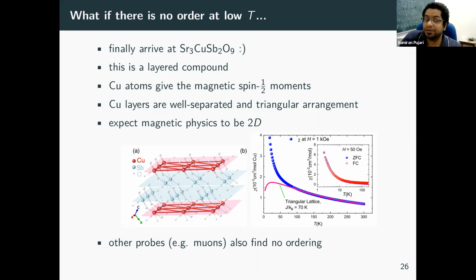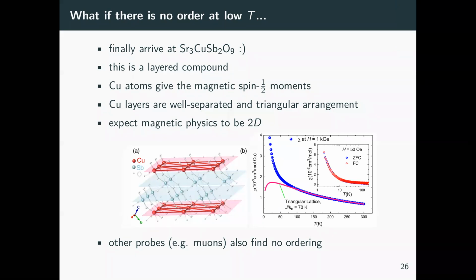That question can be asked even for an unfrustrated square lattice, right? Say I had a pure square lattice. So here it turns out that this goes under the name of Chakravarty, Halperin, Nelson theory. Perhaps experimentally the way it will work out is you measure neutron scattering on a sample, and you have to pay attention to how the line widths evolve with temperature. And that should match up with the prediction of that. I don't know the details, frankly. But the point is, as you said, at any finite temperature you don't expect any order. But how the correlation length grows towards infinity, because at zero temperature it's going to be ordered, there's a sort of precise prediction. Okay. Yeah. Thanks.